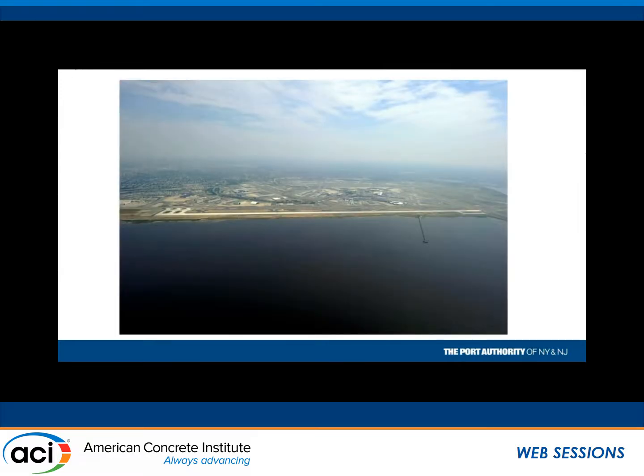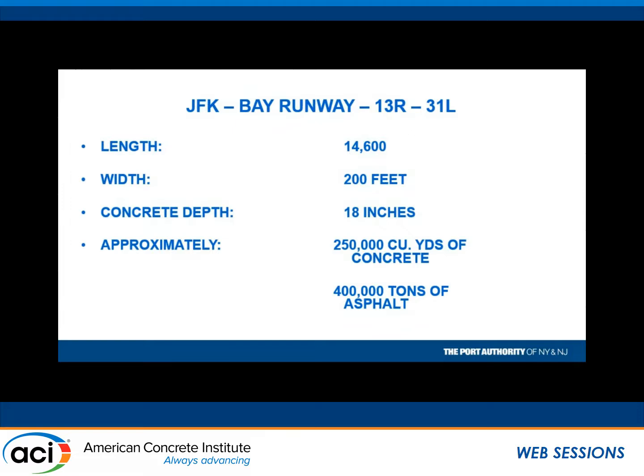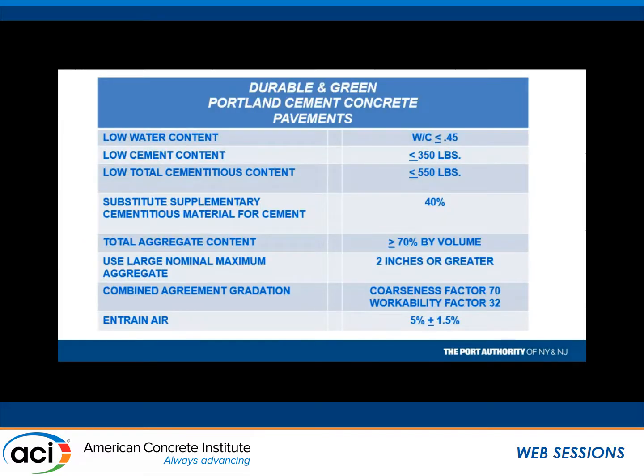This runway is almost 3 miles long. It's the longest runway that we have in our system. And 250,000 yards of concrete were placed, and quite a bit of asphalt too. And here again, we have to abide sort of by the FAA spec. But I met with the FAA and said, listen, we want to take some exceptions to your specification. And they were about 2 pages long, because we don't think what you've got there meets our requirements. So, water cement ratio less than 0.45, that's industry standard. There's nothing peculiar about that.